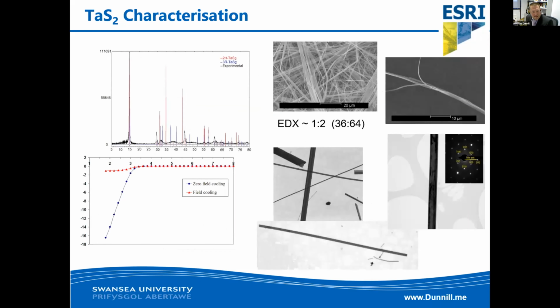Okay, so looking at some of the characterization, we've got the different morphologies with their EDX showing it's approximately 1 to 2. We've got our wires and ribbons. We've got electron diffraction to show us what we've got. And XRD actually shows us that we can get the 1T, the 2H, the 3R polytype structure for the tantalum